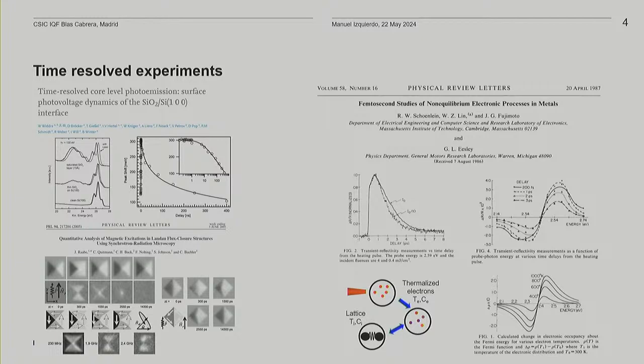This was a study on polycrystalline gold, and basically they excited the material with a laser, 800 nanometers, and then they probed the response as a function of time delay, and you see here that you have already a sub-picosecond resolution. Then they studied this as a function of the fluence at different times, and they modeled this with